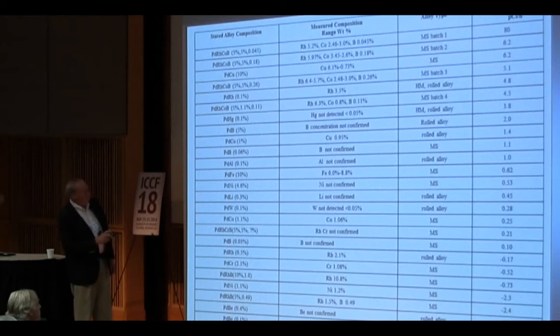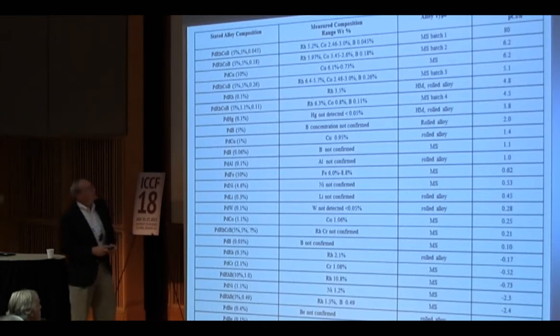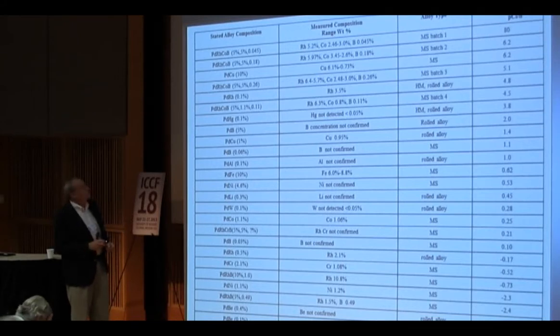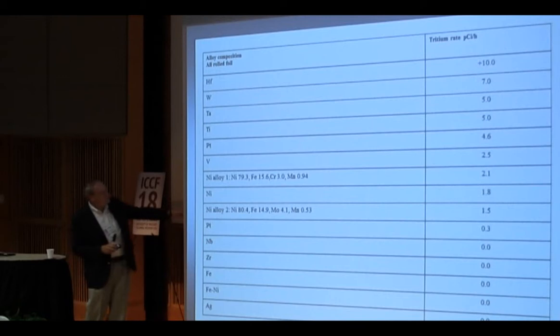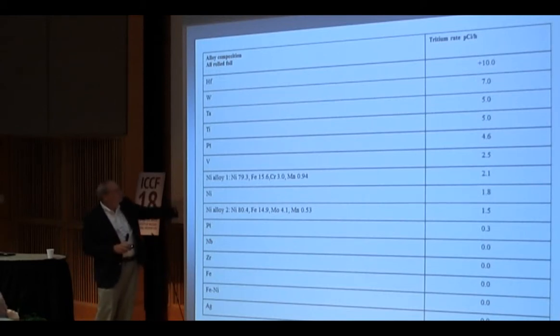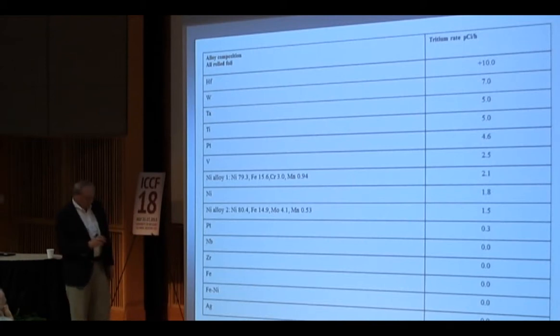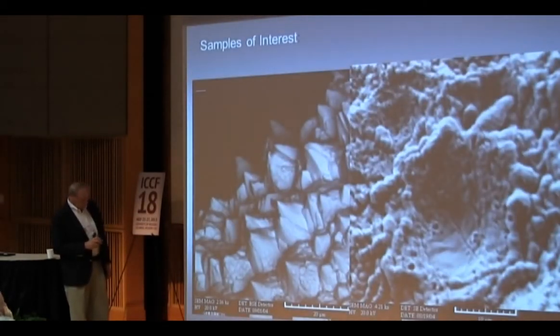So the best one was this particular thing right up here, palladium, rhodium, cobalt, boron. Okay, and we concentrated on that one because that one gave us the most results, the highest tritium results. But this number here, 0.045, that's the first time I think anybody's seen this in a conference. That's a low number for the boron. And later I'll show a sample of that. That was active. They all show some activity except maybe this silver, iron, zirconia, niobium. But nickel works.